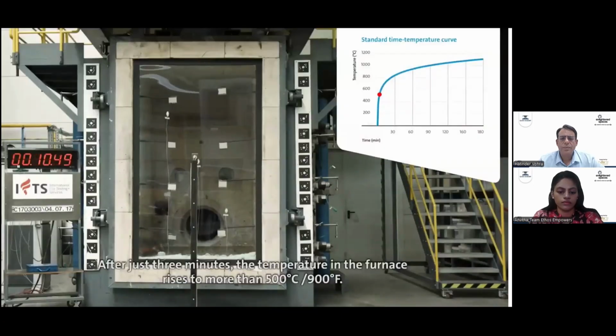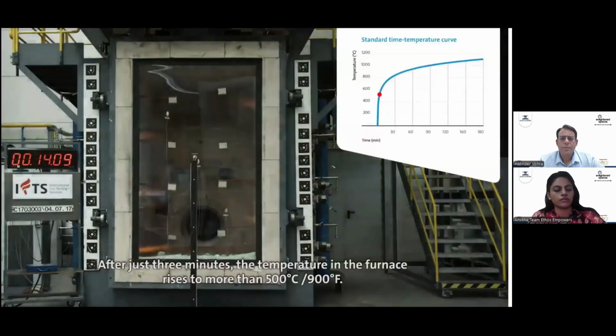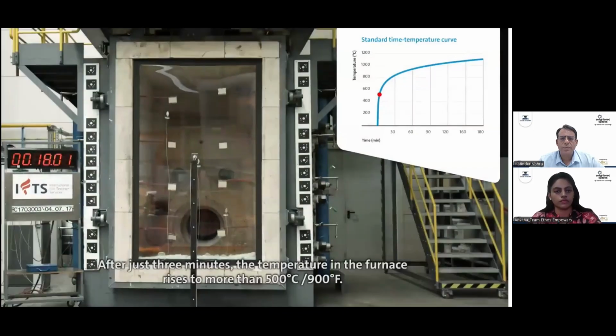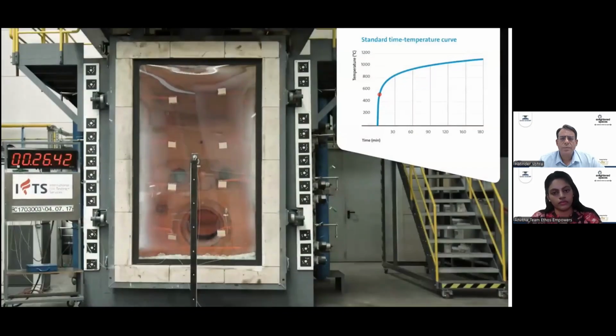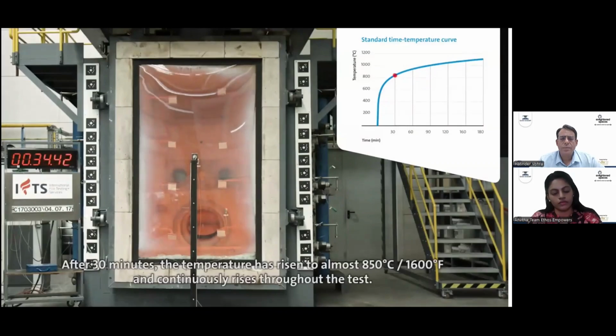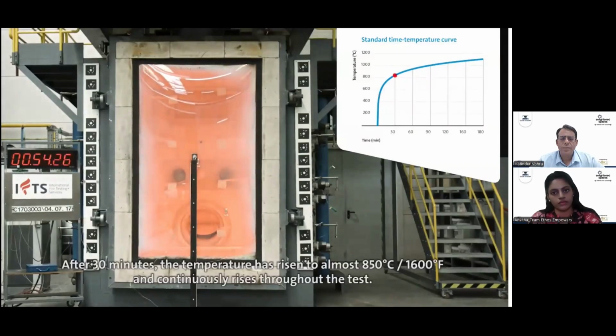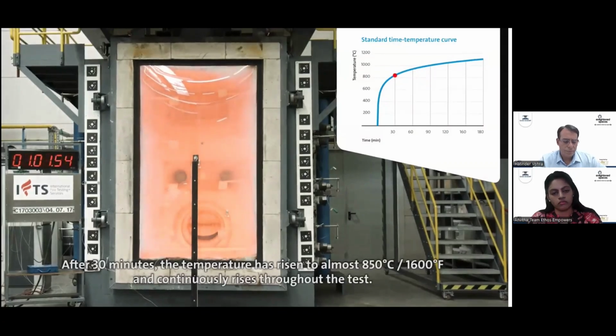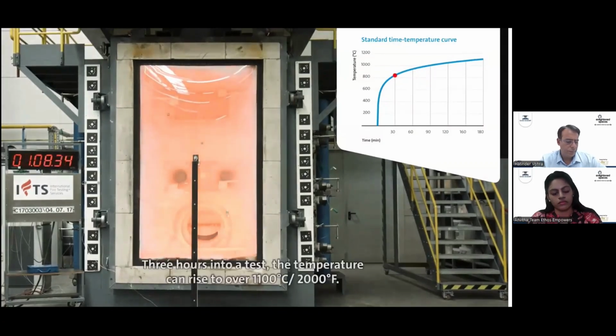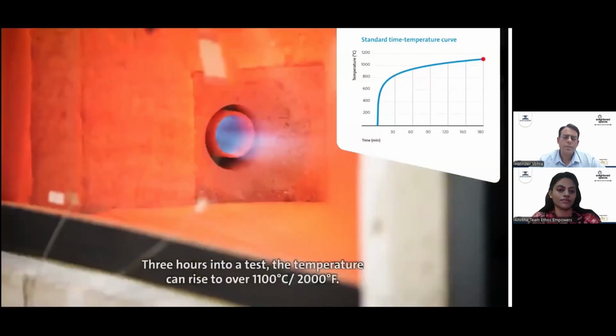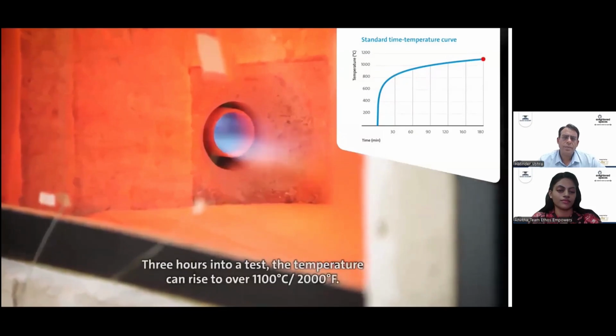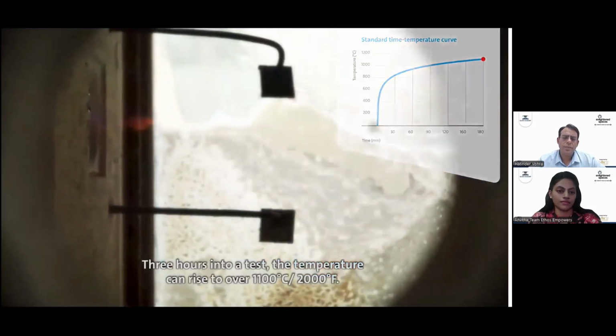After just 3 minutes, the temperature in the furnace rises to more than 500 degrees Celsius, which is 900 degrees Fahrenheit. After 30 minutes, the temperature has risen to almost 850 degrees Celsius, which is 1,600 degrees Fahrenheit, and continuously rises throughout the test. 3 hours into a test, the temperature can rise to over 1,100 degrees Celsius, which is 2,000 degrees Fahrenheit.